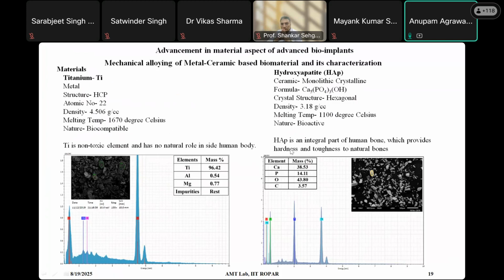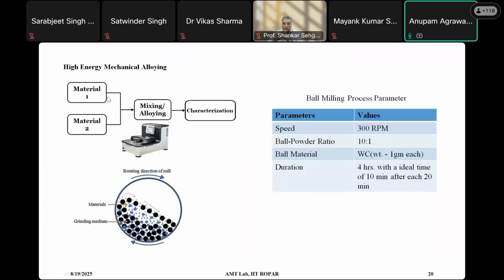this mixed hydroxyapatite, which is an integral part of human bone, and it provides hardness and toughness to the natural bones. Now we try mixing it in different ratios and see if we can get the properties we desire. So different materials were mixed using mechanical alloying, this ball milling kind of process. Several attempts were made, several numbers of hours that we tried, and we found that some of these parameters yield results: speed of ball milling, ball powder ratio, ball parameters, and a 4 hours duration, etc.